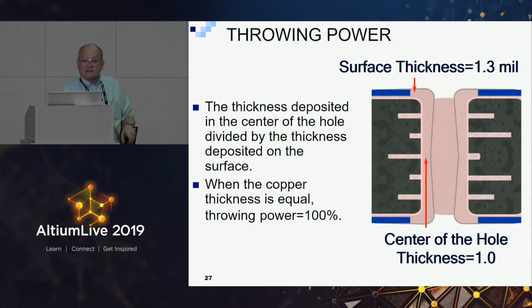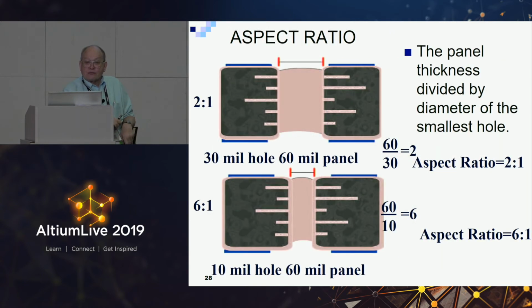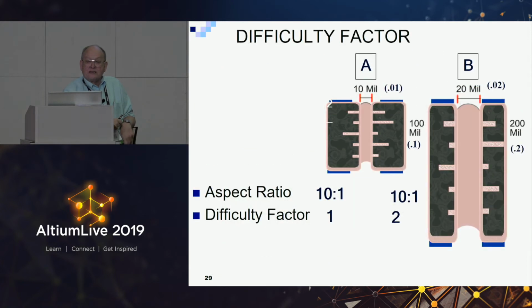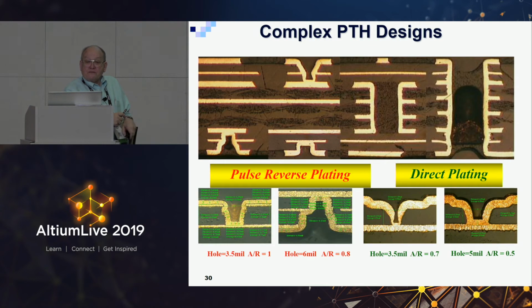Current density in terms of electroplating these holes, a thing called throwing power in terms of the aspect ratios. And this is a little bit more about aspect ratio, how it's calculated, what it is. Difficulty factor. The smaller that stuff gets and the higher the aspect ratio, the more difficult it is for us to physically get fluid into these things. And if we don't get the fluid into it, we can't electroplate it uniformly. And the copper isn't thick enough, it's going to fail through normal use. And so here are some of your iPhones and Samsungs in terms of complex designs of blind and buried vias and stacked vias, et cetera.